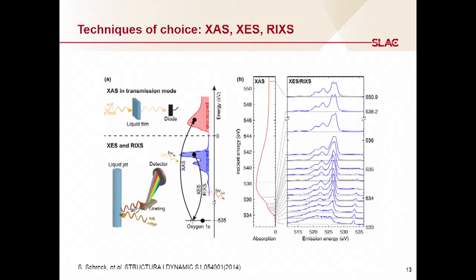And resonant inelastic X-ray scattering is really a combination of these two techniques in one, but it's really one unique event that you promote an electron and another electron rapidly falls down. It's essentially a way of doing Raman spectroscopy. So for those of you who have done optical experiments, Chandrasekhar Raman came up with this Raman spectroscopy idea almost 100 years ago, that the color of the light that you shine on your sample can differ from the color of the light that comes out. And this tiny change of energy tells you what is the excitation that you create in your sample. And this is very unique knowledge that is very precise and very good to know if you have X-rays, because you can tune them to a particular absorption edge, and that can tell you a lot about the system of interest. So we're really after this resonant inelastic X-ray scattering technique.